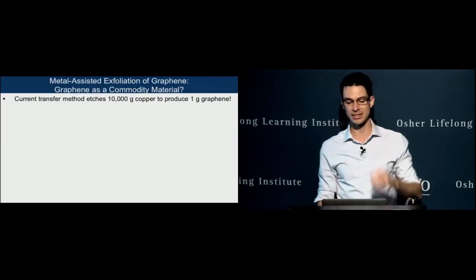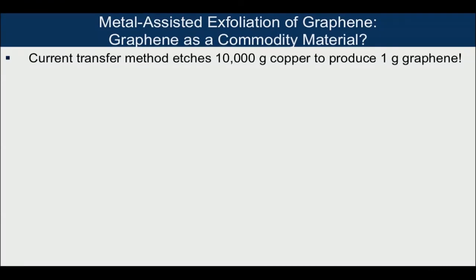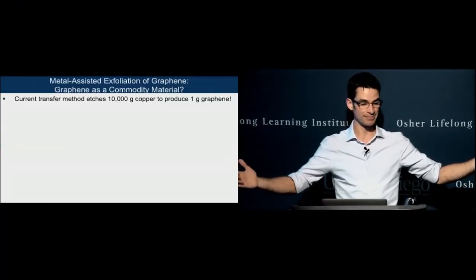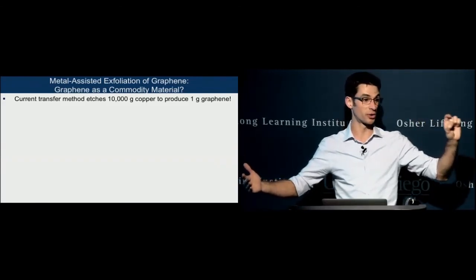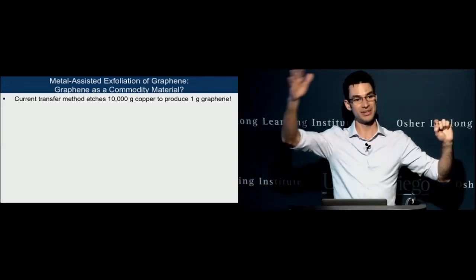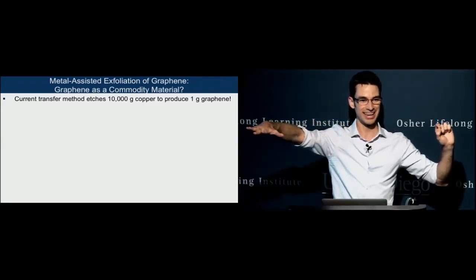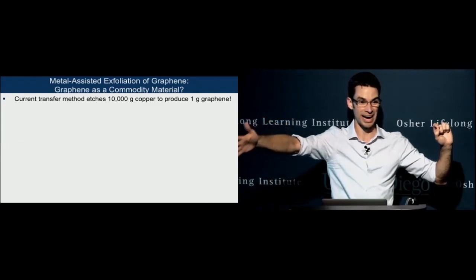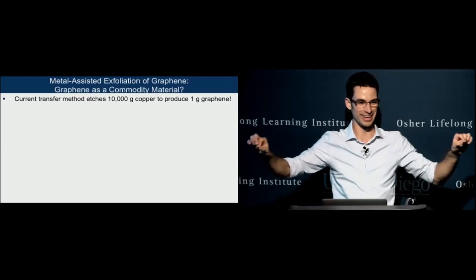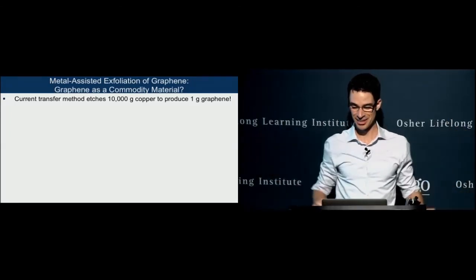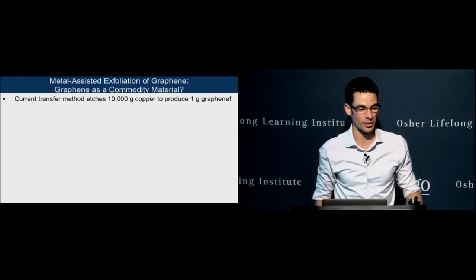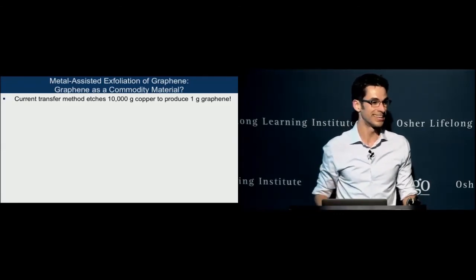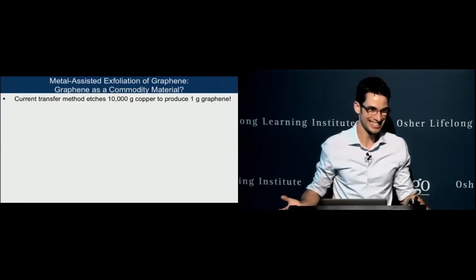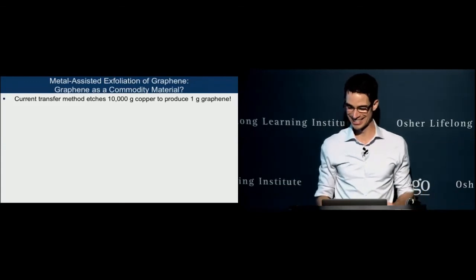science. But the problem is that the current graphene fabrication methods, manufacturing methods, they take a film of super pure copper foil, and it costs a lot of energy to make it. It's 20 to 100 micrometers thick, that's millionths of a meter. Then you deposit this single layer of carbon atoms on top, and then you chemically etch in a toxic acid bath the copper away, and then you get this one layer of carbon atoms for the graphene. Now this takes about 10,000 grams of copper to produce 1 gram of graphene.